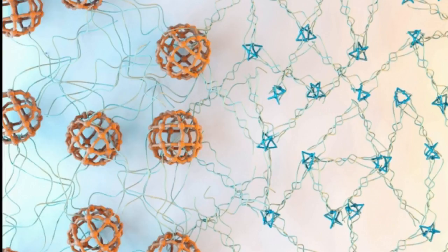When the material is in the small cluster state, it becomes up to 10 times softer and more dynamic. They can flow when heated up, which means you could cut them, and upon mild heating, the damage will heal. This approach overcomes the trade-off that usually occurs with self-healing materials, which is that structurally they tend to be relatively weak. In this case, the material can switch between the softer self-healing state and a more rigid state.